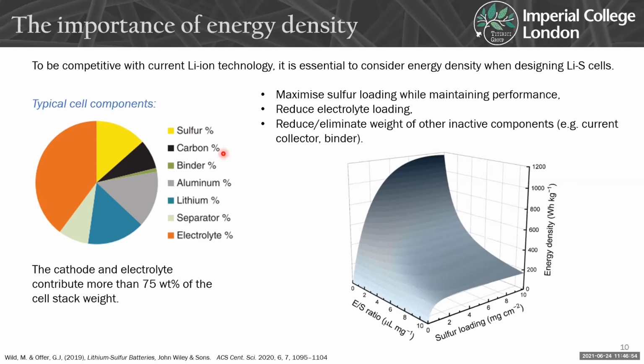So this graph on the right, we've got just the typical cell components. If you think about the cell, we're not just considering the sulfur on its own, but you've got the different additives in the electrode. So you've got the carbon and the binder, you've got the foil, because normally we do a slurry coating onto an aluminium foil. And then we've got a huge mass from the electrolyte, and then the lithium anode, and then the separator. Actually, the cathode and the electrolyte contribute more than 75% of the cell weight.